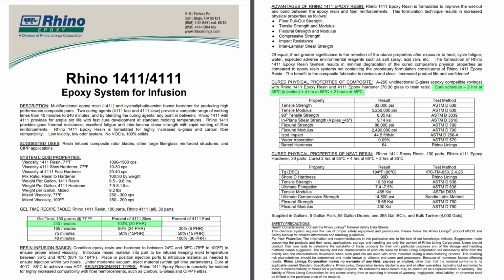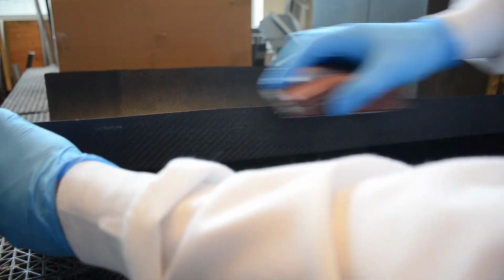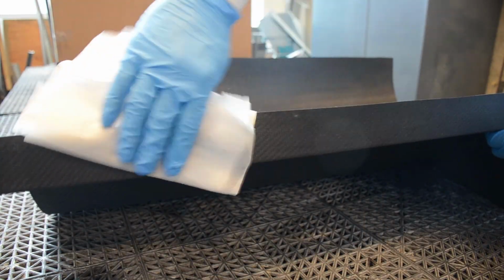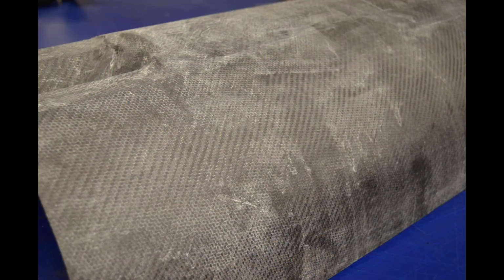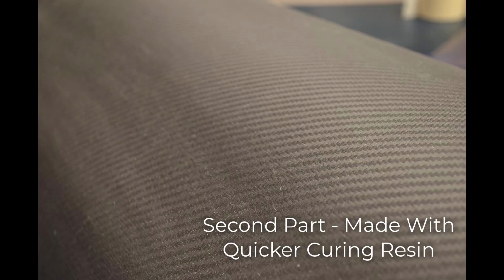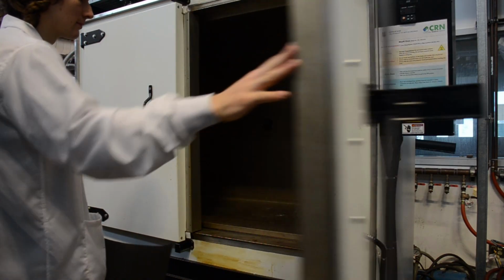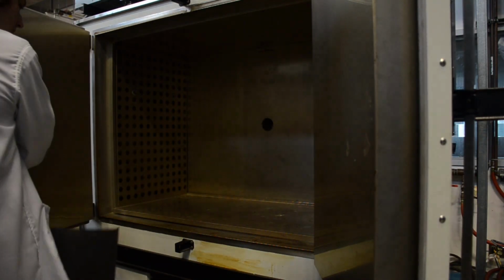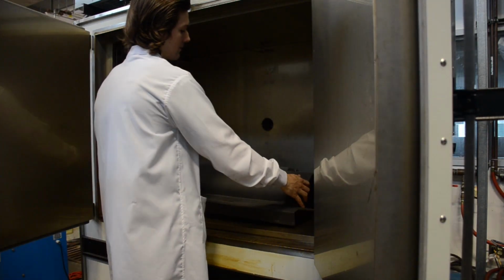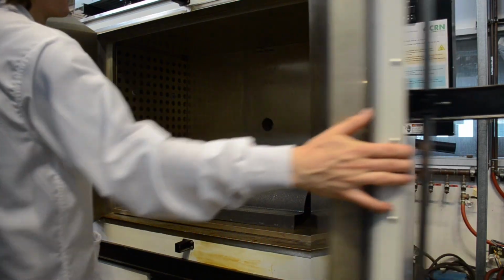The third part was removed from the tool after 24 hours at room temperature. It was then trimmed to size and the dust was removed with a moist towel. The dust became embedded in the outside surface, which did not occur with the second part, which was made with resin with a shorter cure time. This was likely caused by the very slight softness and tackiness still present in this slow curing resin. To prevent this, a heated post-cure or increased time at room temperature could be used to increase the degree of cure before the part is processed.